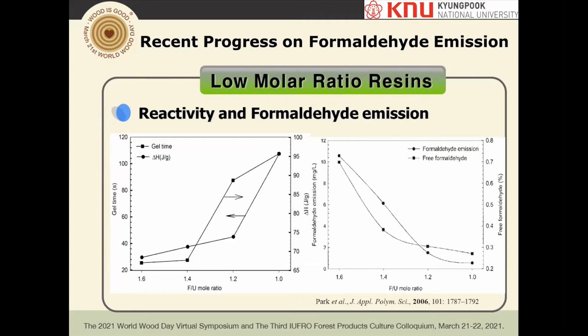What people are doing is reducing the molar ratio to have a low formaldehyde emission. And then I'm going to tell you what's happening when you have low molar ratio resins. What I did is I prepared different molar ratio UF resins like this, and then we tested the various properties. First of all, the gelation time is increasing, and also delta H, which is the energy to cure the resin, is increasing when you have low molar ratio resins. That means that when you reduce the molar ratio, you lose reactivity and need more energy. But when you have the low molar ratio resin, you have less emission, that's for sure. And also you have less free formaldehyde in the resin after cooking. So that means you have less emissions.